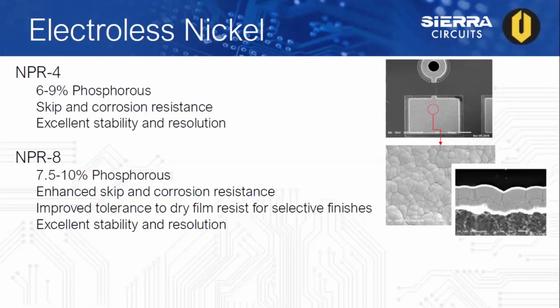Now the NPR8 is a newer generation bath and deposits 7.5 to 10% by weight phosphorus. By having a lower stabilizer content and also depositing a higher phosphorus content compared to the NPR4, this NPR8 bath provides enhanced corrosion resistance and higher plating initiation on the substrate or panels.